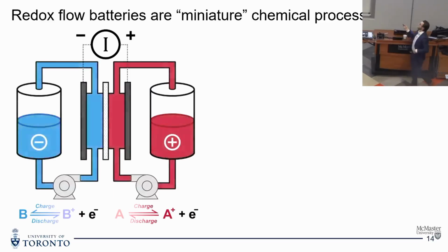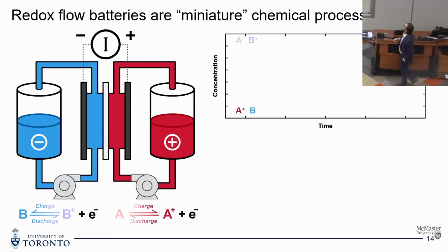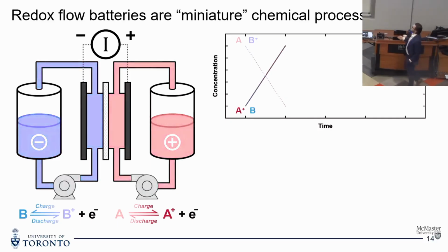So if we charge our system, we go from A and B plus to A plus and B, and think about our concentrations of each of these species. Generally speaking, these concentration changes are linear, with the slope of that change being proportional to the current. Again, this is what you would expect in a mass balance for a constant reaction rate. So you get this linear change over time. And then we discharge the system back. We apply a current in the opposite direction to extract energy out of our battery. And our concentrations reverse course and go back essentially to our starting state.